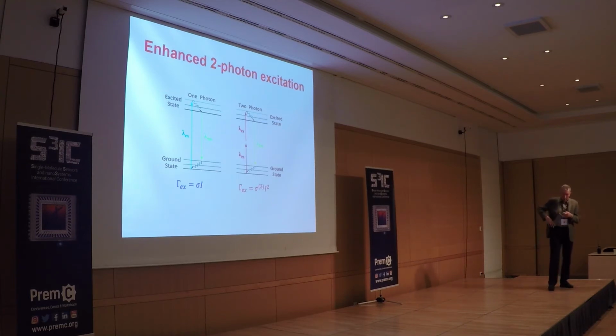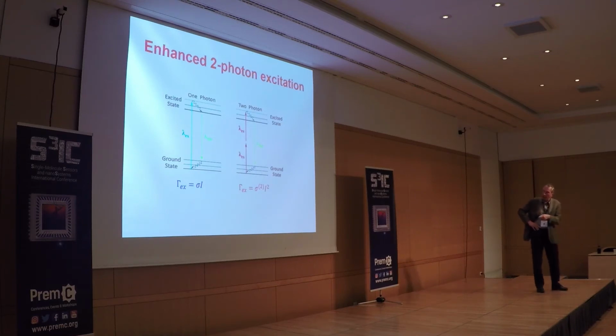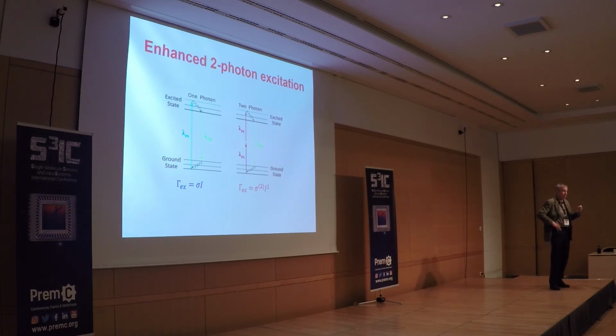So we can do that. The idea of the experiment is shown here. It's very simple. With one photon, the excitation probability is proportional to intensity. If you go with two photons, this will be proportional to the square of intensity. So we try to enhance this step here twice. So we need a nanorod with a plasmon which is resonant with the fundamental frequency of the laser that pumps two-photon excitation, not the overtone or the second harmonic.